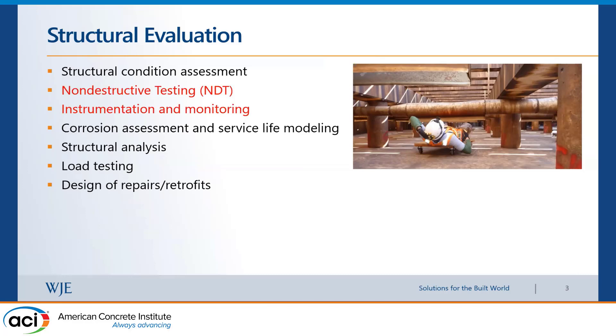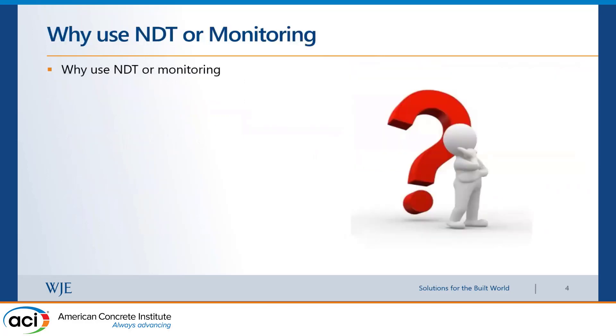Once we find we need to know more, we go to NDT or instrumentation and monitoring to collect more information. We also do corrosion assessment and service life modeling, which can follow instrumentation or non-destructive testing. For structural analysis, we sometimes rely on field measurements — for example, if you don't have as-built drawings, you use GPR to get rebar depths and spacing, then do an inspection opening to find the bar size. We also do load testing, which relies on instrumentation for deflection or strain measurements, and finally we design repairs and retrofits.